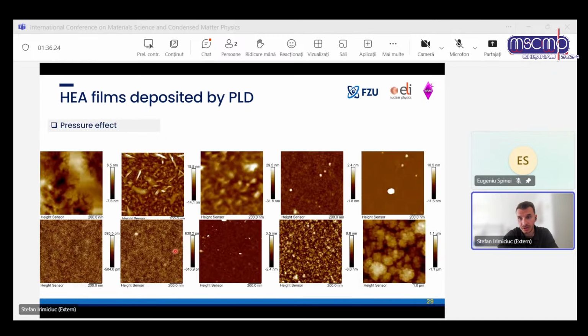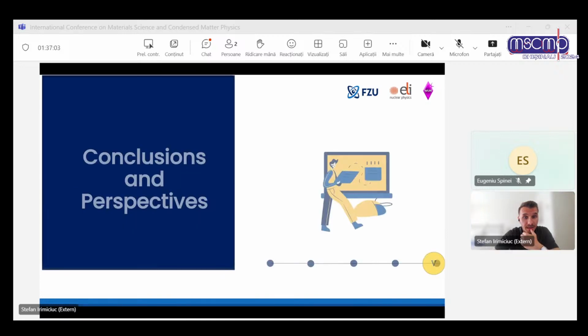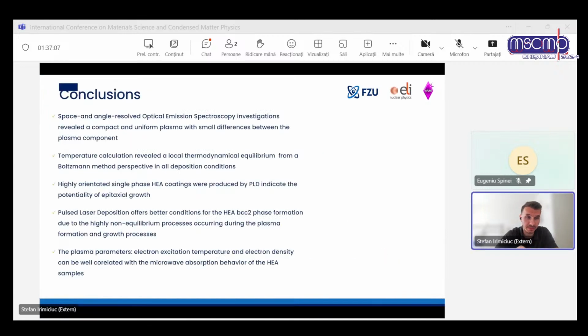And this is a really, really nice evolution of what happens with the oxygen this time. And I put this specifically at the end just because it's always nice to end with a pretty AFM picture if you have it. You can see the crystallization changes, but this time a better look shows us that actually the flat surfaces that we saw still have some really, really small nano structuring. And in the end, we get this really nice cauliflower oxides, high entropy oxides, which will further be used for other applications as well. And with this, I think I'm in time.